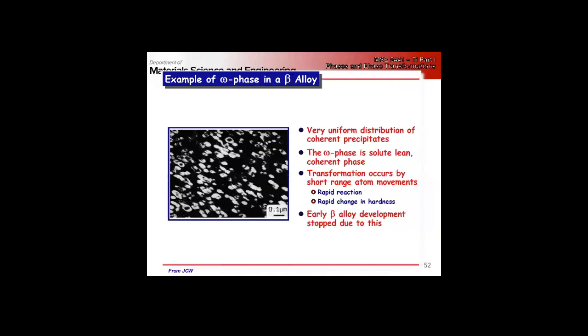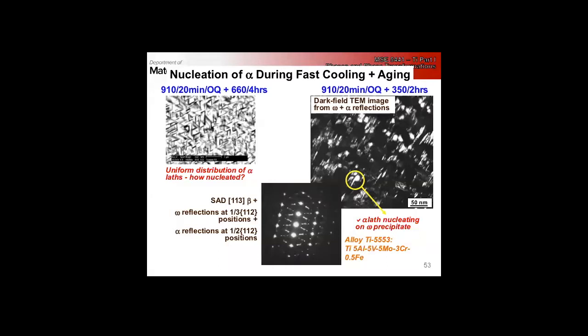So this is in some ways very much like bainite in steel. You have a transformation that goes by coordinated atomic motion and then diffusion of the carbon out. Here we have collapse of the BCC structure into the simple hexagonal or non-close packed hexagonal, and then beta stabilizers come out, and this is really beneficial, as we said before, for uniform distribution of alpha laths. So it's heterogeneous nucleation. Here we see alpha nucleating on